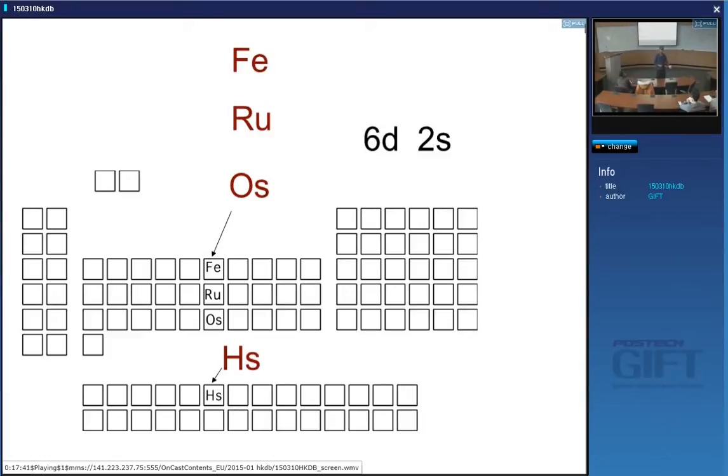Hexagonal system does not have that unless you bring in additional modes such as twinning and so forth, which introduces other complications, okay? So if iron was not body-centered cubic at room temperature, we would be in trouble. And why is it body-centered cubic, whereas ruthenium, osmium are not?